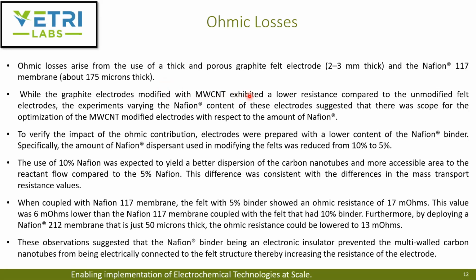overall resistance. So to verify their impact and the ohmic contribution, they prepared the electrodes with lower content of the binder, which they add when they make the electrode. So reducing it from 10% to 5%. So the use of 10% Nafion, of course, was expected to yield a better dispersion of the carbon nanotubes and more accessible area to the reactant flow compared to the 5% Nafion.